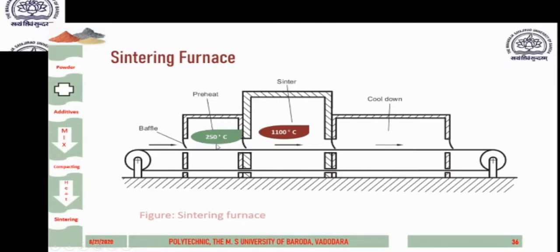We have seen this process in our heat treatment chapter, where the temperature rises to the final temperature, then there is soaking time, and after that we cool or quench it. Here we don't have to cool or quench it. Once it reaches 250 degrees centigrade, it should remain in this furnace only. Since the furnace is stationary and the part is moving, the part should be moved at a velocity so that it remains 40 or 45 minutes at 250 degrees centigrade after it achieves that temperature.